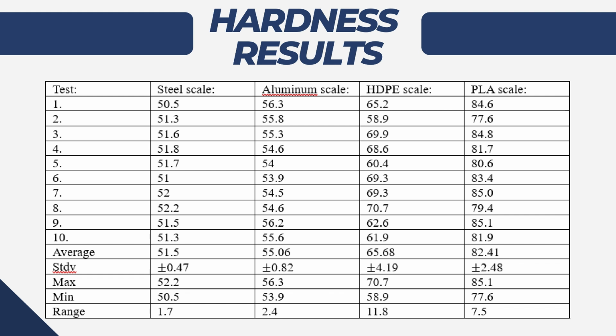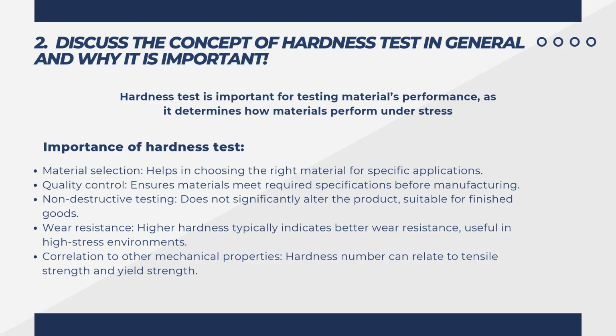We can also measure polymer materials such as HDPE and PLA using the Shore hardness test. For this experiment, we get an average hardness number for HDPE of 65.68 with a standard deviation of plus minus 4.19, and for PLA an average hardness number of 82.41 with a standard deviation of plus minus 2.48. So we're moving on to question number 2, where students need to discuss the concept of hardness test